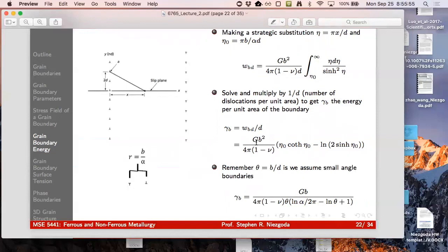So it's just easier to think of it as a generalized surface energy or a surface tension. And we know the grain boundary doesn't exhibit a long-range elastic field. So the number of problems you can get at by thinking about it from an elastic strain is fairly minimal.